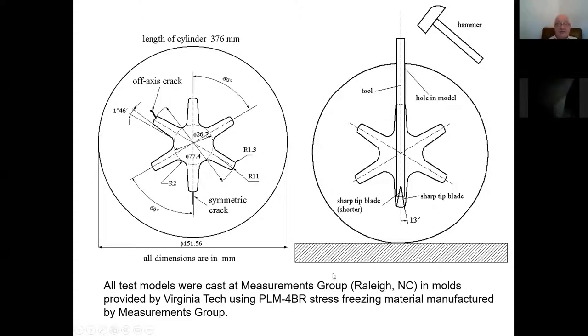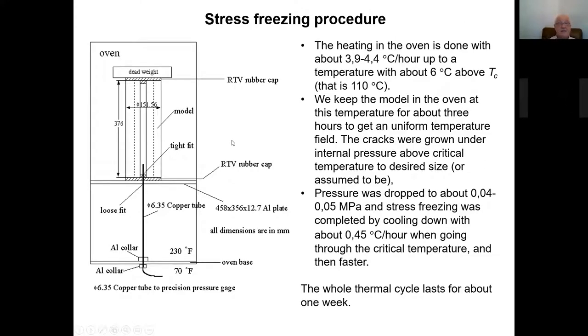So essentially, you can drill a hole, you can use such a device, which is kind of a sharp blade. You can initiate, by hitting with a hammer, the crack going on axis and off axis. And of course, then you have to grow this crack naturally by applying internal pressure. We're going to see this. Well, these models were cast at Measurements Group, at Vishay, as it is called, and the stress freezing material was, of course, also from this company.